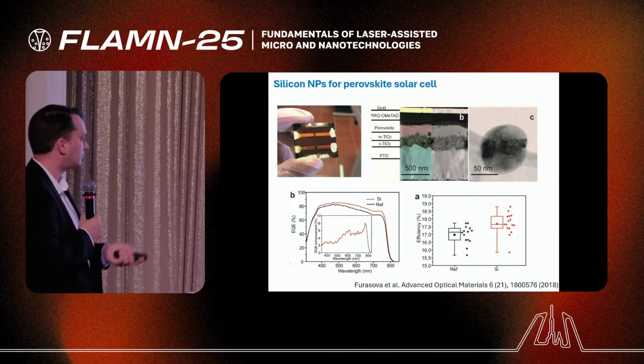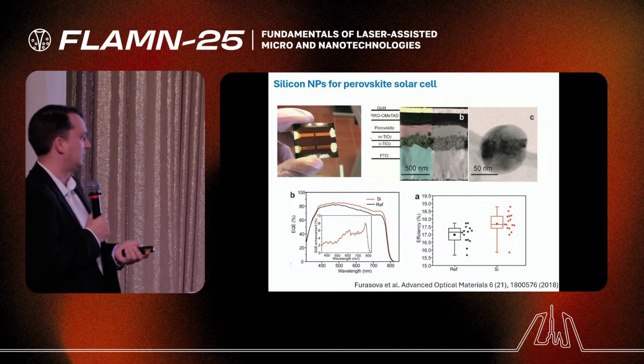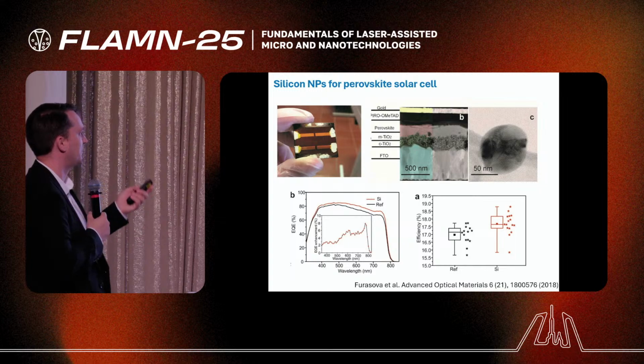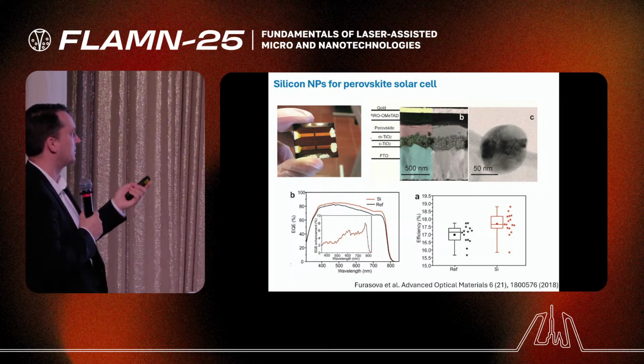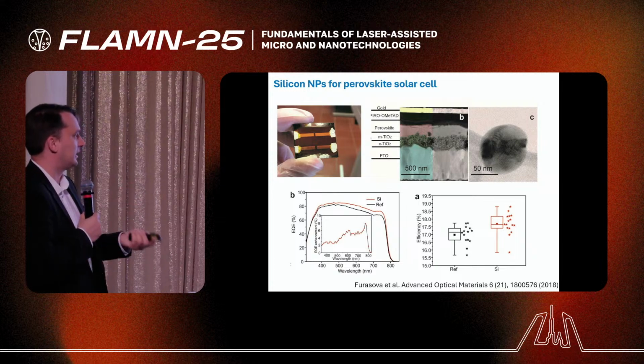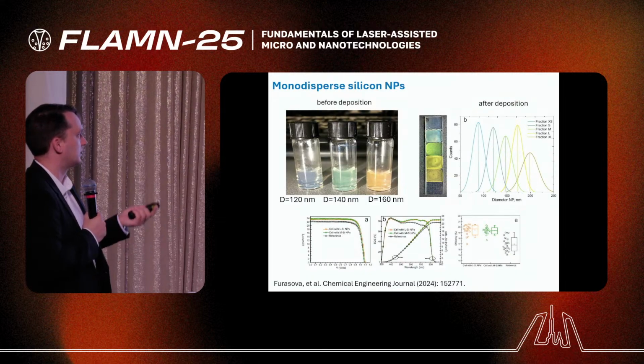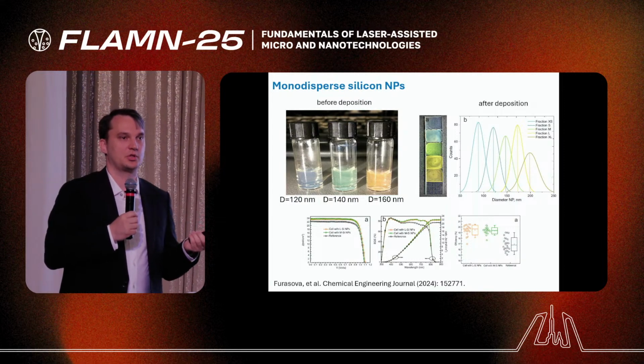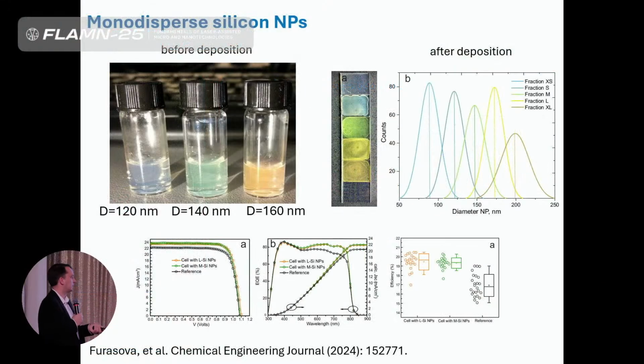Here are some examples made by our former PhD student Alexandra Furasova. Today she will also give a talk about this direction, so I will just briefly mention it. In perovskite solar cells we can introduce such nanoparticles and improve absorption and eventually efficiency. The nanoparticles can also be not just of broad size distribution, they can be of different sizes, so we can select a particular size. You see that after selection each solution has a different color because of resonant light scattering in each nanoparticle. It's also a good approach for creating colorized solar cells, which are good for building-integrated photovoltaics and for some design approaches. And also, in principle, laser ablation is quite a universal technique.